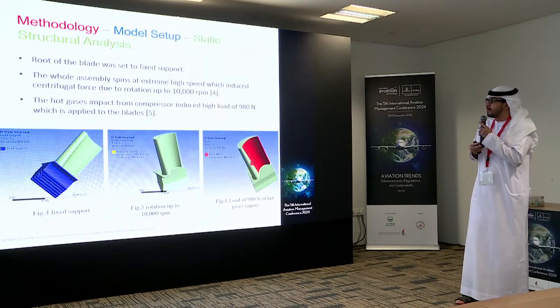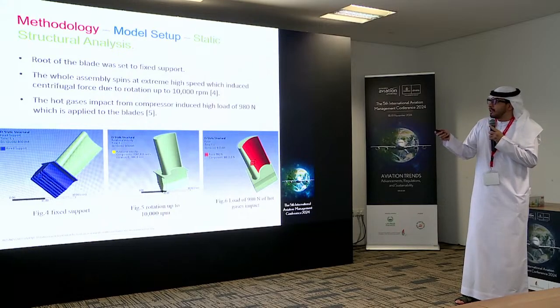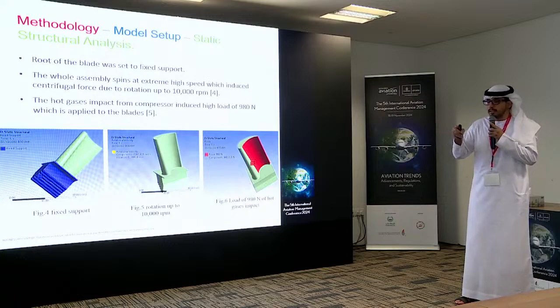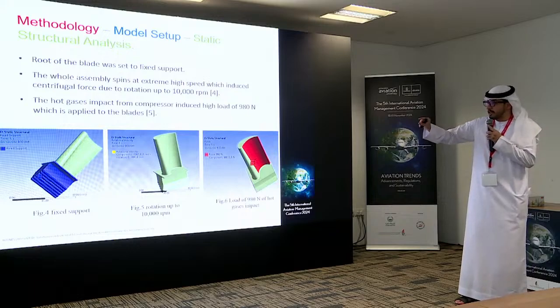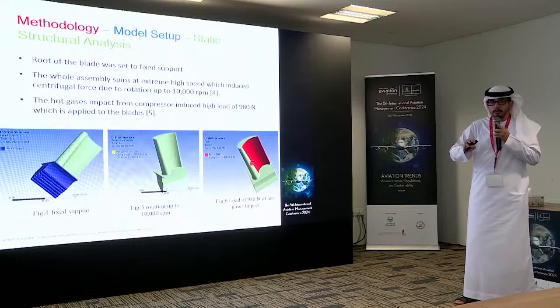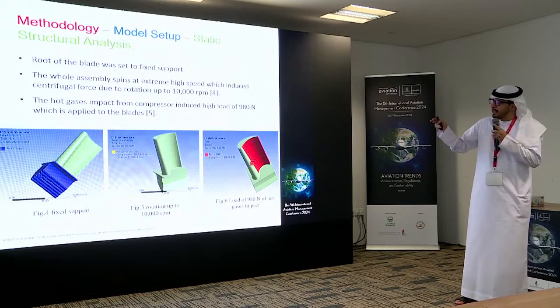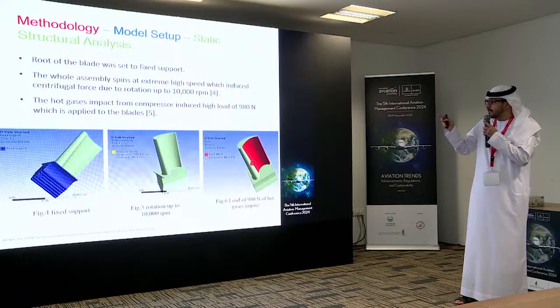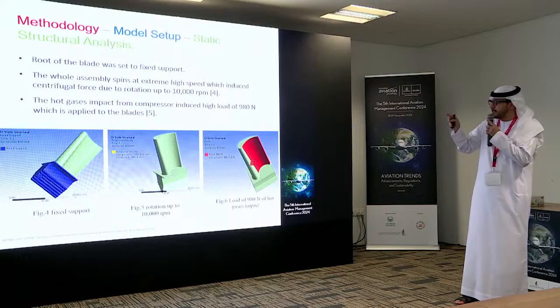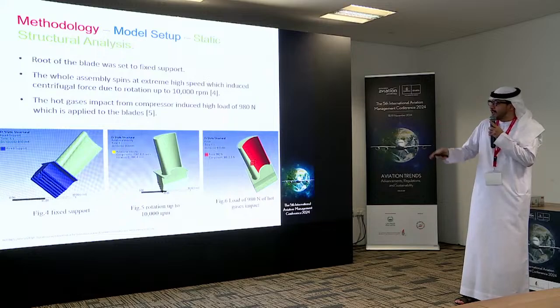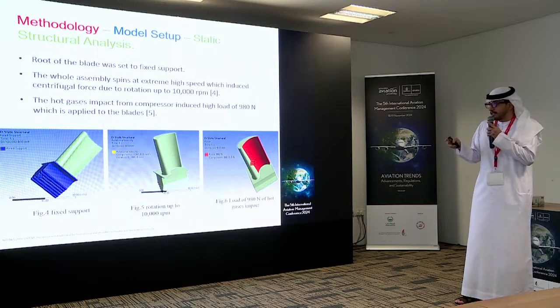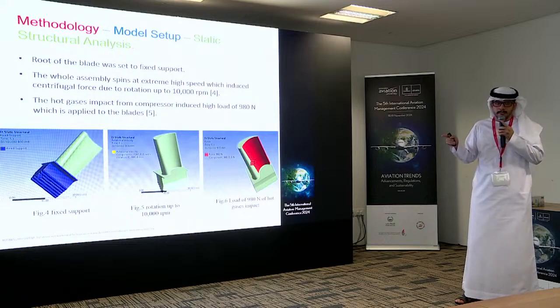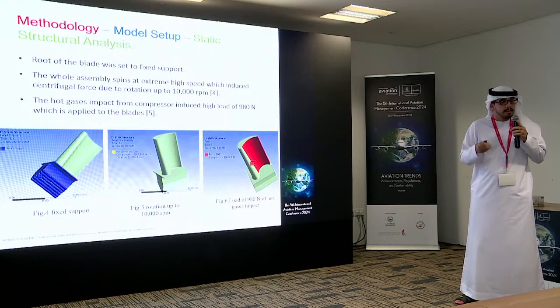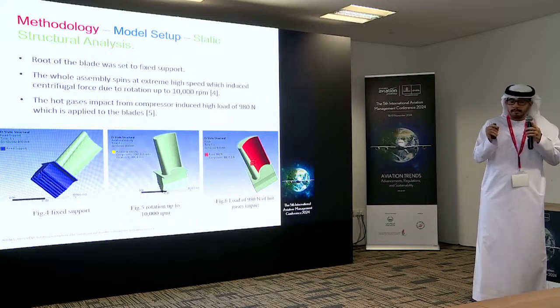Now we move to the first part, which is the static structure analysis. The root of the blade was set to fixed support. As you can see in figure 4, the base of the blade itself is fixed to the turbine disc. So in order to fix it, we assign it to be fixed in its place to ensure no movement in any of the 3D directions. The whole assembly spins at extremely high speed, which induces a centrifugal force due to the rotation, up to 10,000 RPM. In figure 5, of course, the turbine will rotate up to 10,000 RPM, so we had to include it in our simulation. This centrifugal force will cause a deformation.